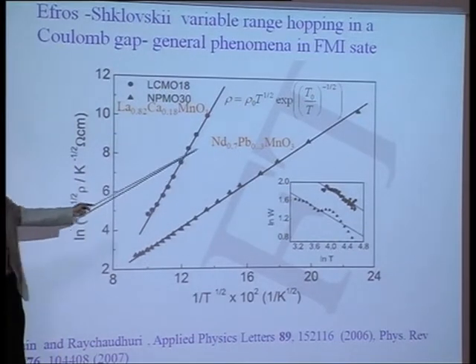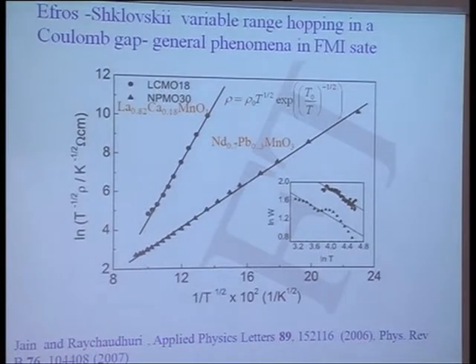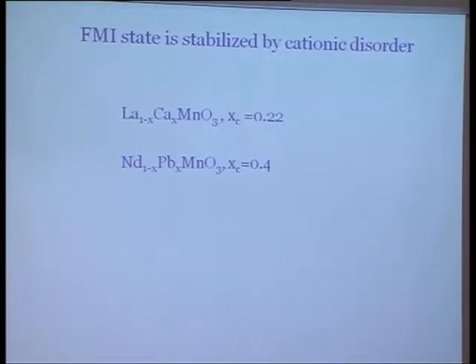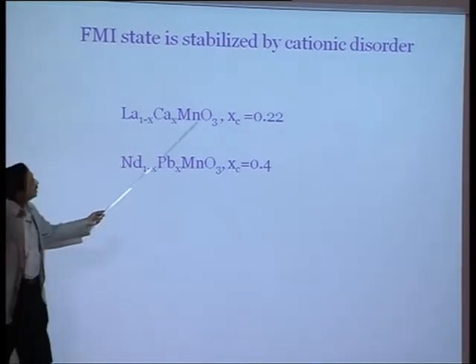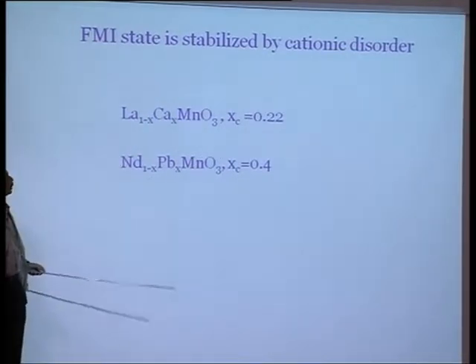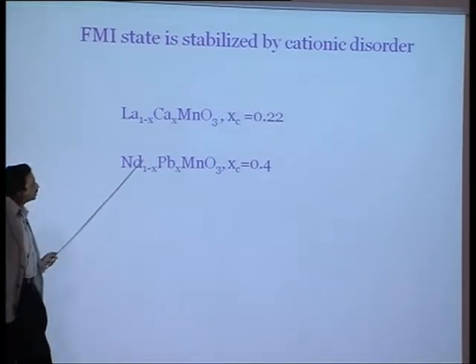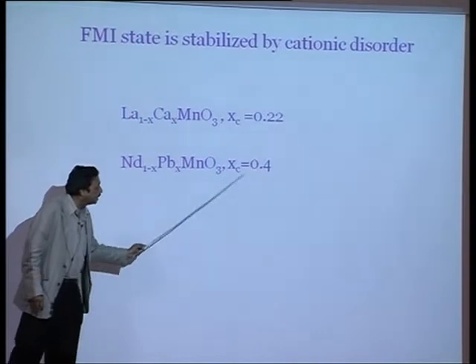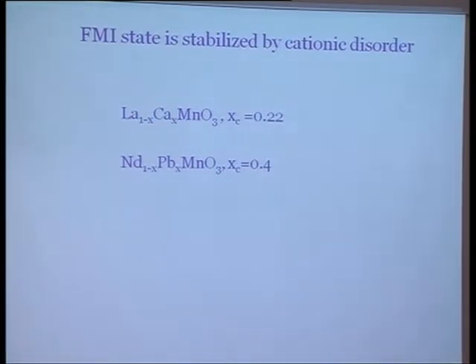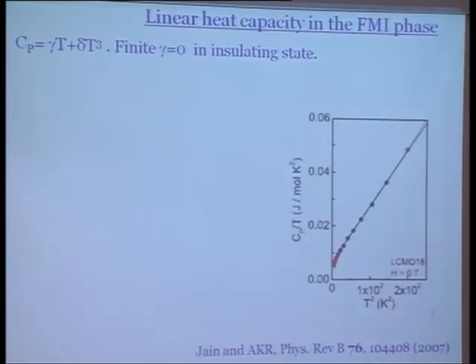This is a homegrown crystal made by Professor Bhatt's group, and here also you see that this kind of hopping relation is valid. There is one very interesting piece of information, that this insulating state is actually stabilized by cationic disorder. If you take this material, this is the critical composition when the metallic state shows up. If you take this material where the disorder is much more, where the cationic radii are very different, then this is where you see the metallic state coming in. So cationic disorder is an extremely important ingredient in this kind of material.